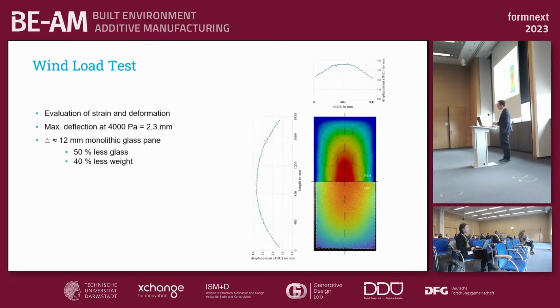And just to compare it a little bit to other glass structures, that would be roughly the same deformation which you would get with a 12 millimeter monolithic glass pane, so one solid glass pane. And that already means that we save 50% of the glass used, and we only have 40% less weight, because we are adding a little bit of weight during the additive manufacturing process.